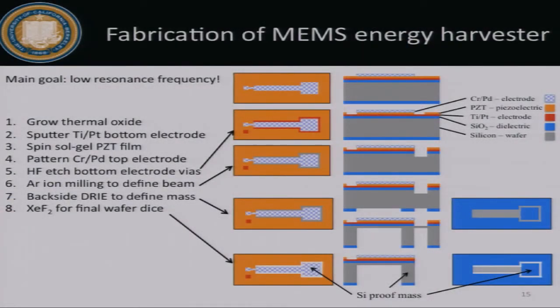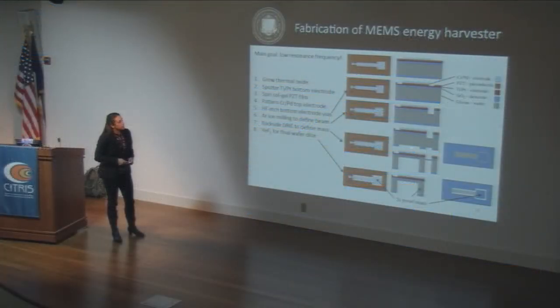So real quickly, the MEMS fabrication steps that I used to build the first device. I started with a blank silicon wafer, which is gray, grew a thermal oxide layer, which is the blue color, then sputtered a titanium platinum bottom electrode, which is red, and then sol-gel spin deposited the piezoelectric layer, which was PZT, lead zirconate titanate, the orange layer. Then the first masking step was patterning the chrome palladium top electrode, which is checkered here, and then etching with HF to reveal the bottom electrode, and then another etch using argon ion milling to reach down to the silicon layer, then backside etching to remove the oxide and silicon, and this big chunk becomes a mass at the tip of the beam. This becomes the beam. The final step was to etch away this little connecting silicon layer to leave a freestanding beam. So this is the beam with piezoelectric material.